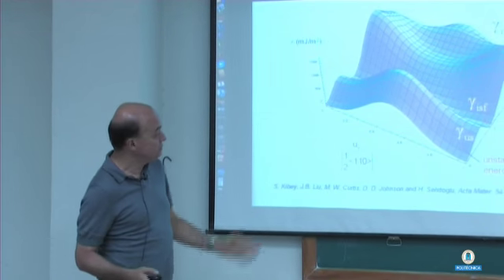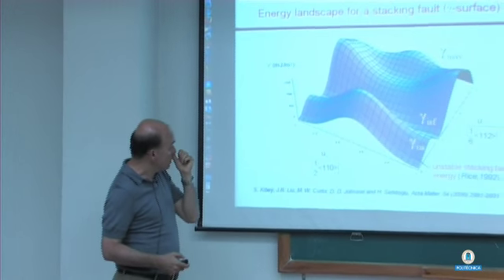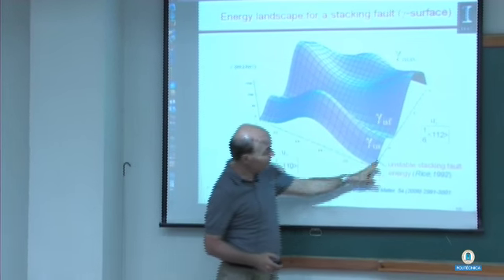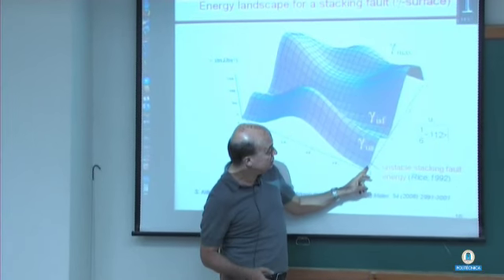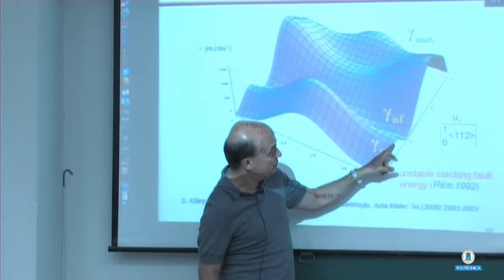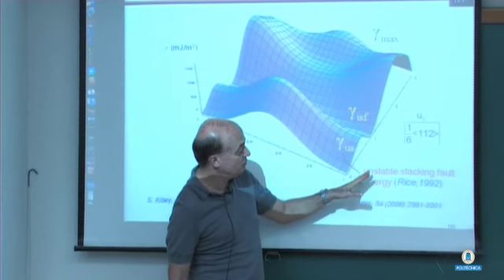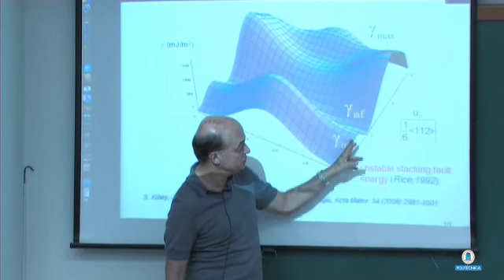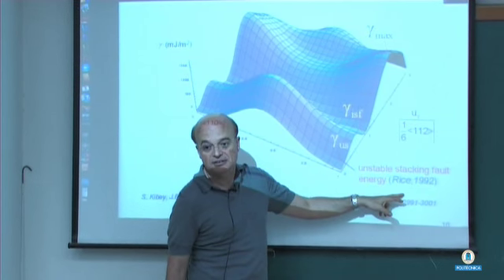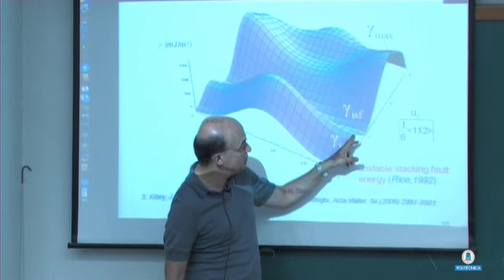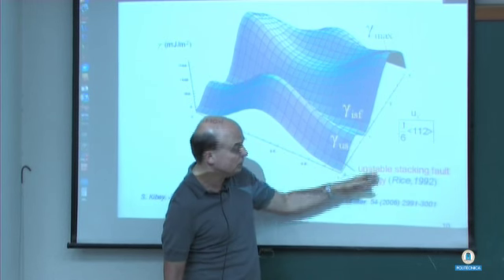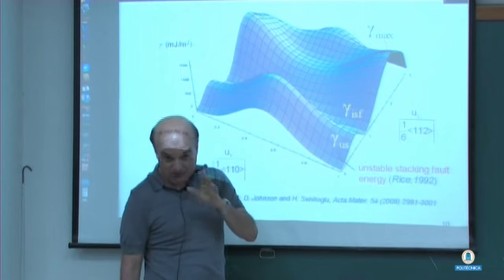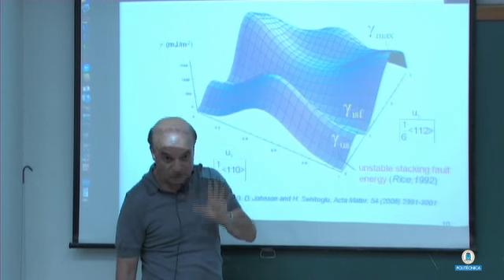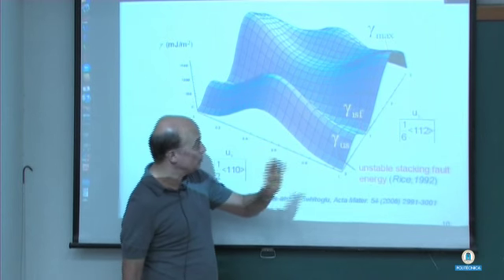And if you plot this in 3 dimensions, if you do the calculations in 3 dimensions, this is the path that we just investigated, okay? So that's gamma US. By the way, the term unstable stacking fault energy was coined by Rice in 1992, associated with this point. This is the intrinsic stacking fault. It has implications in slip, it has implications in fracture and all these things as well. But I'm not going to talk about those.